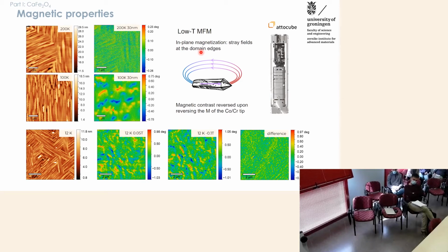So if you look at this image, there is quite some correlation between the end of the needle crystals and the magnetic contrast. And to verify this, we can also do these measurements inside an applied field, which is low enough to not revert the magnetization of the film, but actually reverse the magnetization of the magnetic tip in the AFM. And if we reverse the sign of the field, we get the opposite contrast in the MFM image, which means that now the tip and the films are coupled with a ferromagnetic or antiferromagnetic coupling.